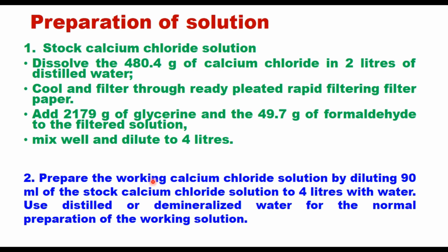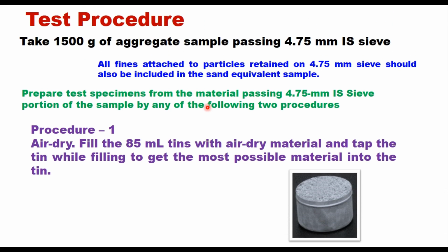The working calcium chloride solution is prepared by diluting 90 ml of this stock calcium chloride solution to 4 liters with water. And distilled water or demineralized water can be used for the normal preparation of working solution. The procedure can be explained in 4-5 steps.